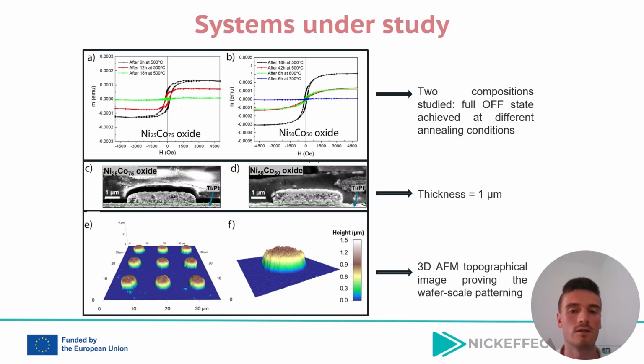To present the material of interest for this work, two oxide compositions, namely nickel 25 cobalt 75 and nickel 50 cobalt 50, were investigated, achieving full off states through different annealing conditions as shown by magnetic hysteresis loops in figures A and B.